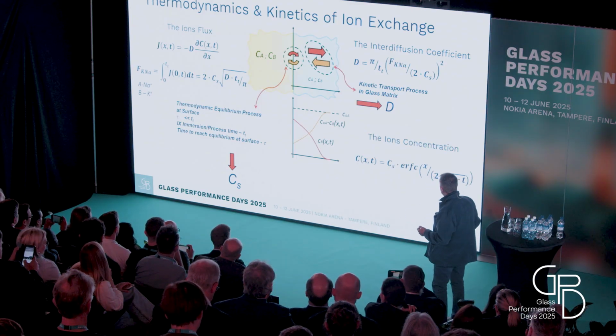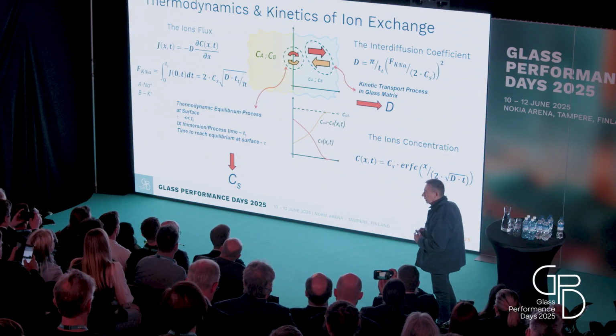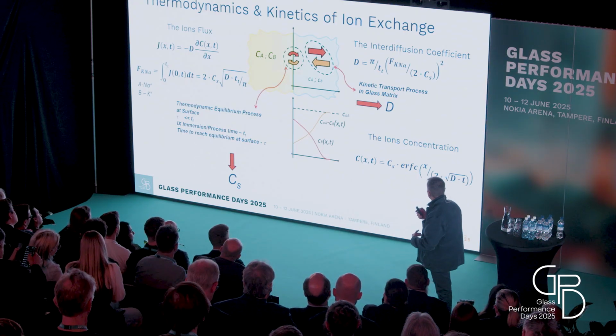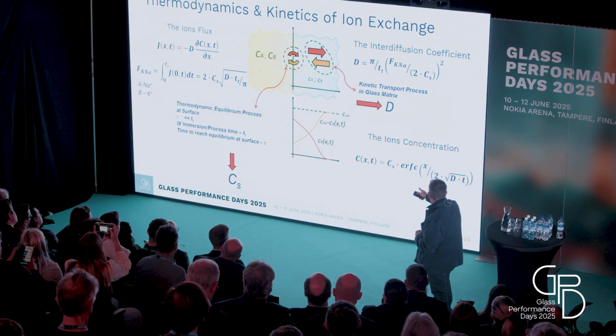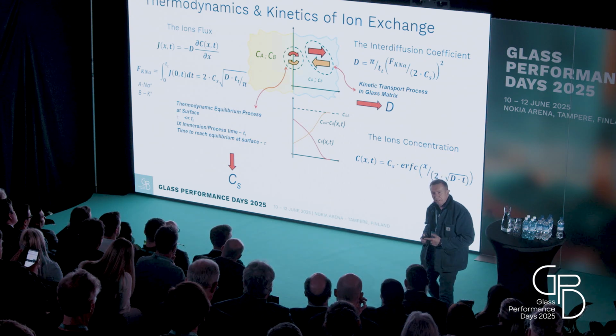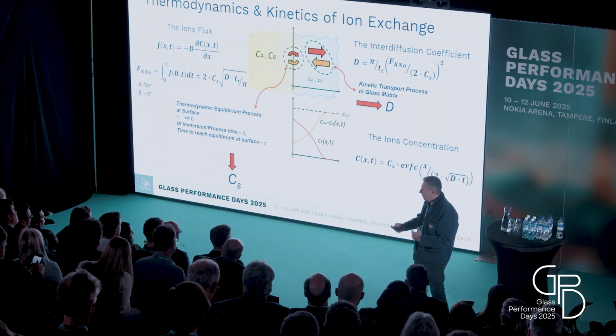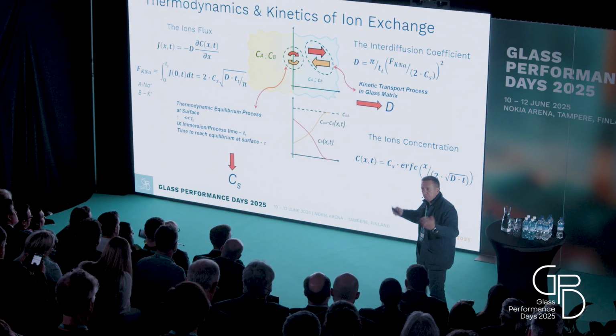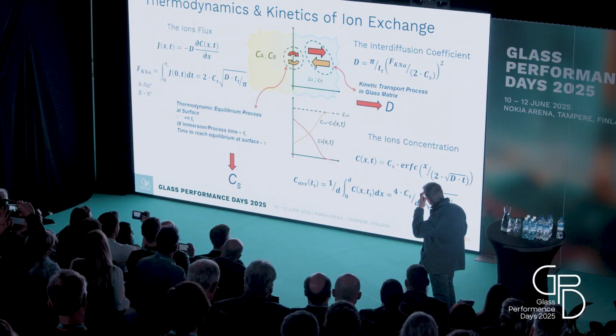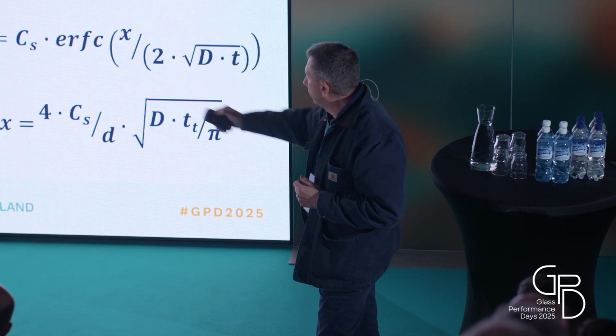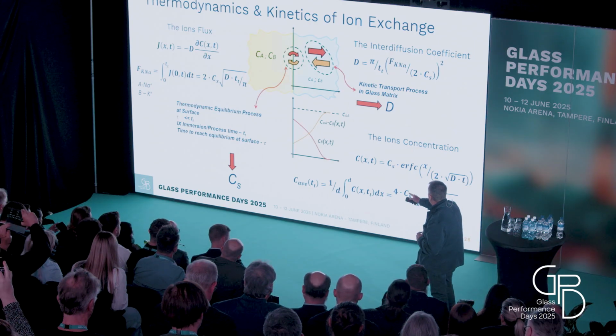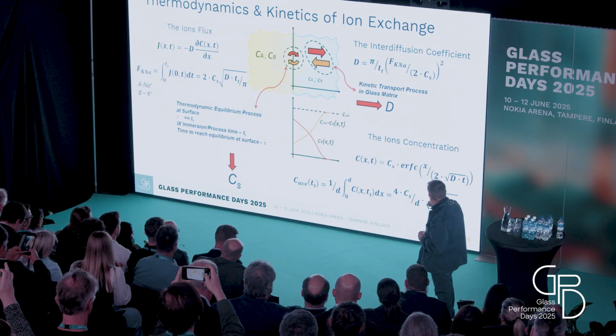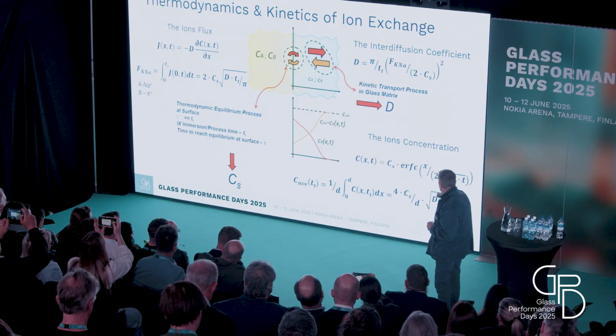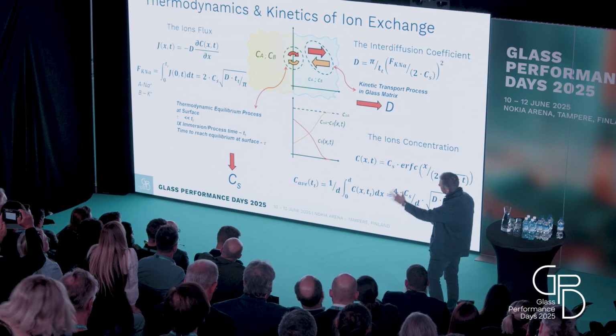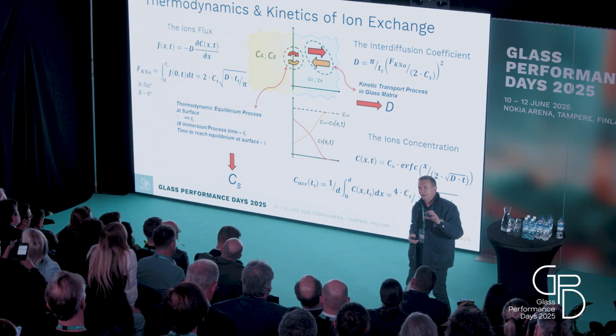So this allows you to define a mathematical function representing the ion concentration in the glass. You see the red curve there, and this is expressed in terms of a special function, a complementary error function. It is not a normal function, but can be calculated with most of the tools that you can find. The other interesting thing is the average of that one. The average of the concentration is just the integral over the thickness of the concentration, and can again be expressed in terms of surface concentration, thickness, interdiffusion coefficient, and total time. This is a simplified theory. It's very simplified, but it works for most of the applications that we have seen.